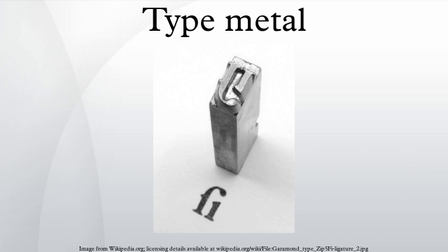Once the temperature reaches 291 degrees Celsius, lead crystals will start to form, increasing the cohesion of the liquid alloy. At 252 degrees Celsius, the mixture will start to fully solidify, during which the temperature will remain constant. Only when the mixture has fully solidified will the temperature start to decrease again.